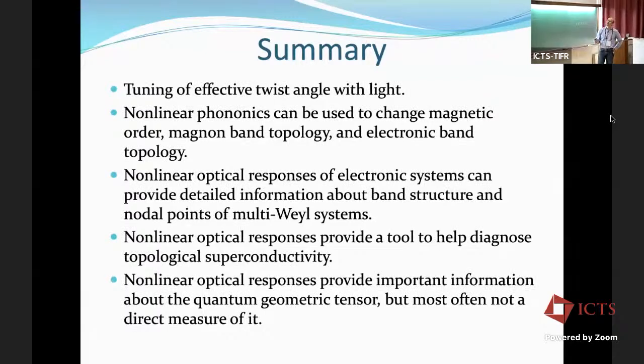So we have seen in the beginning that we could tune the effective twist angle of 2D materials. It wasn't specific to graphene, that's the example I gave, but it works for TMDs as well, by using light that's emanating from a waveguide, which gives a longitudinal component to the vector potential. We used nonlinear phononics to change the magnetic order in bilayer systems, and in the case of manganese bismuth telluride and manganese bismuth antimony telluride, we could also change the electronic band structure.